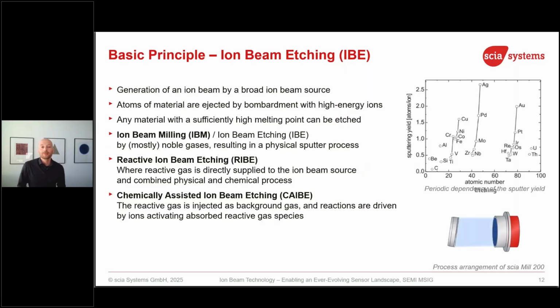Just a clarification, because there are different types of ion beam etching or ion beam milling. If we say ion beam milling or ion beam etching, typically it means we just use noble gases. It's a physical sputter process. There is also something called reactive ion beam etching or chemical assisted ion beam etching, where additional reactive gases go into the ion beam source or just in the chamber close to the substrate in order to tune, for example, selectivities to get higher etch rates. In the following examples, I will focus only on ion beam etching and ion beam milling.